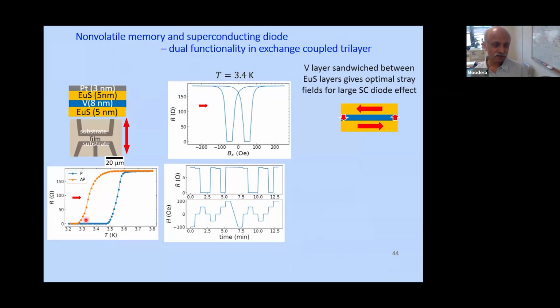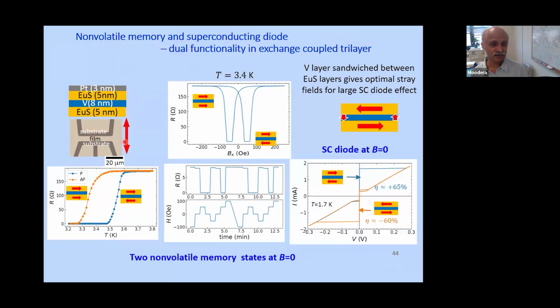So what we have here is that the superconducting transition temperature depends on the orientation of magnetization of the two layers. In the parallel case, you have a lower superconducting transition, with a higher transition temperature for the anti-parallel case, because the field that is seen by the superconductor is enormous because of the exchange field. Now you can see also this kind of behavior. This is what the memory is about.